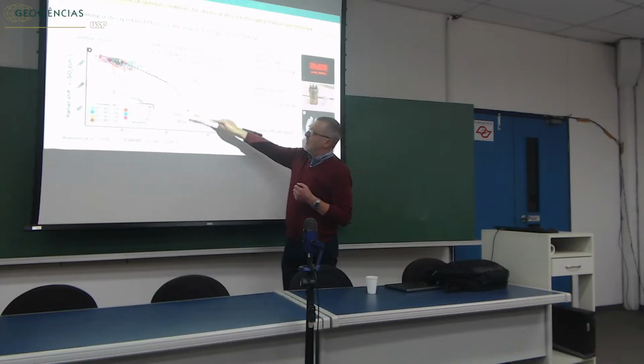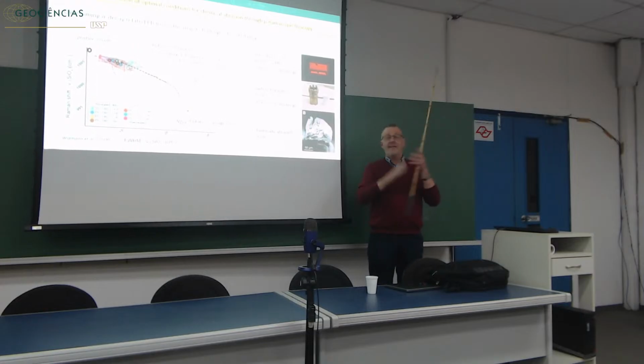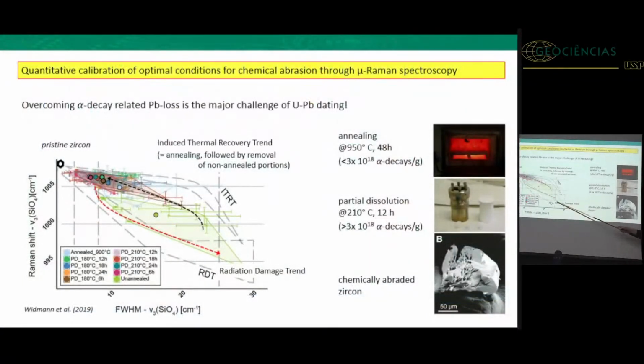And we can even quantify and control this using Raman spectrometry. So this is the Raman shift. This is the position of the main band for zircon, at 1008, and this is the full width at half maximum, so the width of this Raman peak. And zircons which undergo decay damage will follow this trend, the radiation damage trend, and then we do annealing. So the annealed parts will follow this trend here, the induced thermal recovery trend, but we will not manage to get up too much. But then we dissolve away the rest. And with the remnants here, we hope to get as close as possible to pristine zircon.